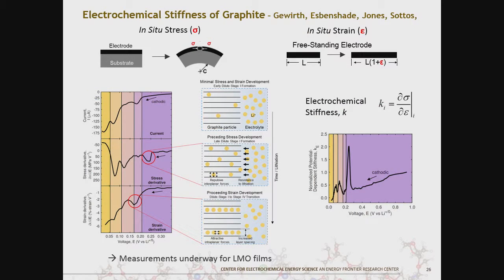So the last bit, this is actually not LMO work, but it's a capability that we're using. This is Andy Gewirth's group and Nancy Sottos' group. There's some very interesting combination of stress measurements, which is when you lithiate and you have your electrode on a substrate and it causes the substrate to bend, as well as strain, which is the change in volume. Typically one studies one or the other. What's interesting is to study both of these things, so they've come up with the idea of electrochemical stiffness, where they can watch the lithiation process, and there are a lot of interesting results on this stuff. There'll be a talk on this later this morning from Andy Gewirth.